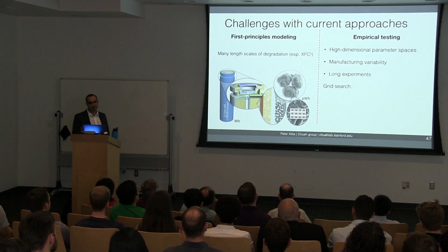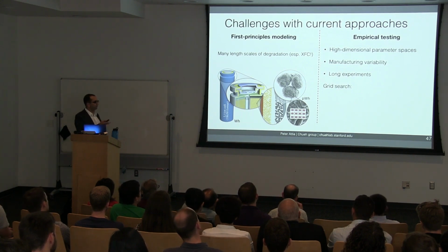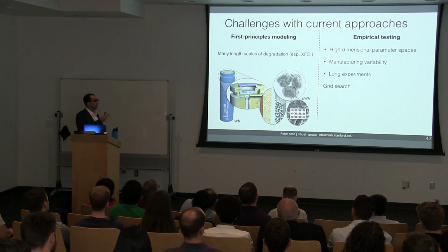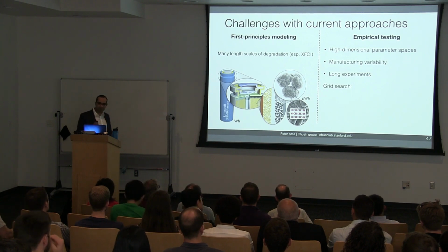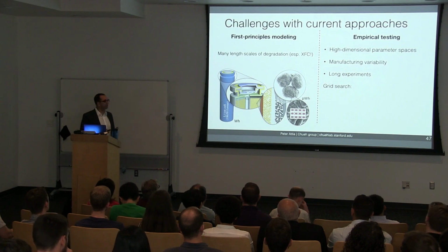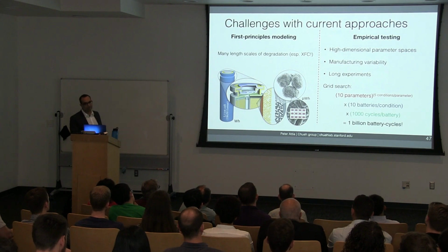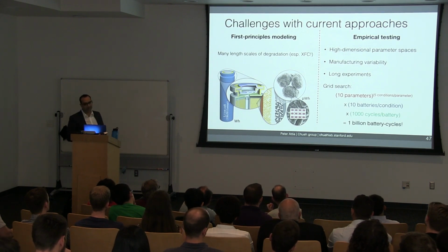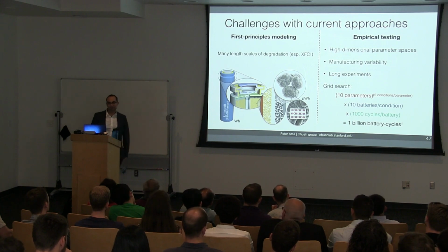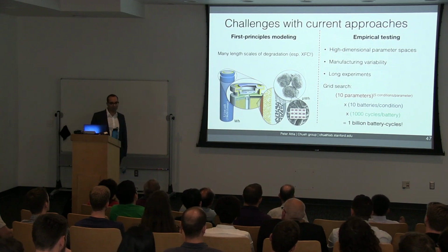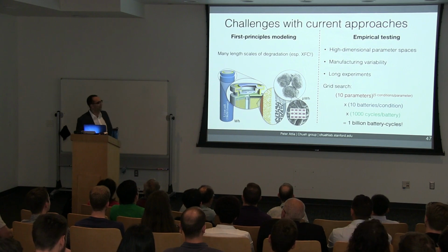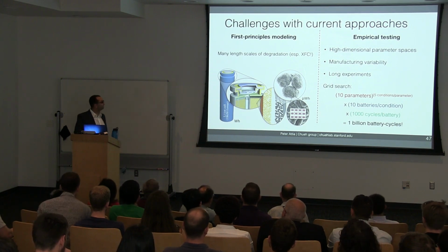The natural alternative is top-down empirical testing. There are a number of challenges associated with this. For one, there's a large number of different fast charging protocols to test. 2, there's really high manufacturing variability. So if you cycle the same cell the same way, you get something like 40% difference in cycle life. And 3rd, battery lifetime is just really long, often taking months to years for mature chemistries. So if we do a quick back-of-the-envelope calculation for a typical parameter space, we get something like 1 billion battery cycles needed to be cycled. 1 billion battery cycles means it'll take me probably another 30 years to graduate. Bottom line here is ain't nobody got time for that.